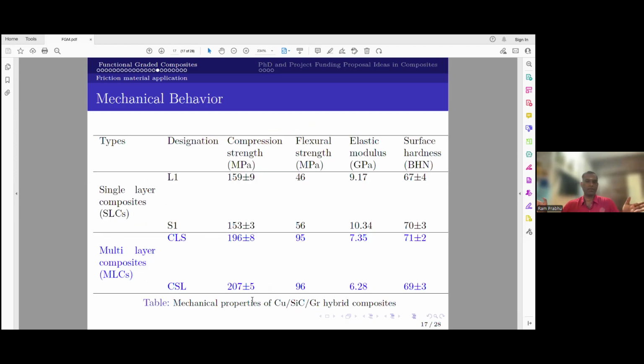And the next is the mechanical behavior related to the braking application: the compression strength, flexural strength, elastic modulus, and surface hardness. Elastic modulus was calculated from the load versus deflection curve. Again you can see that this composition and particle gradient, a multi-layer or functionally graded composite, gives better compression strength and better flexural strength than existing composites. Surface hardness remains the same because in single layer or multi-layer, the surface composition remains the same. So we don't see any change in the surface hardness.